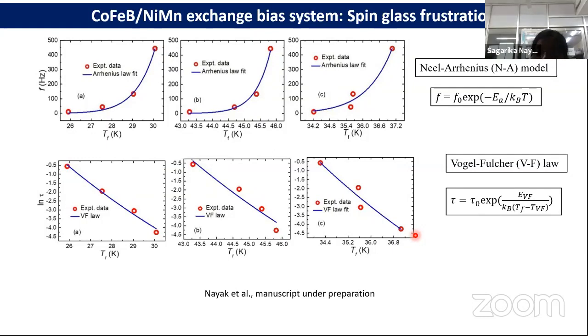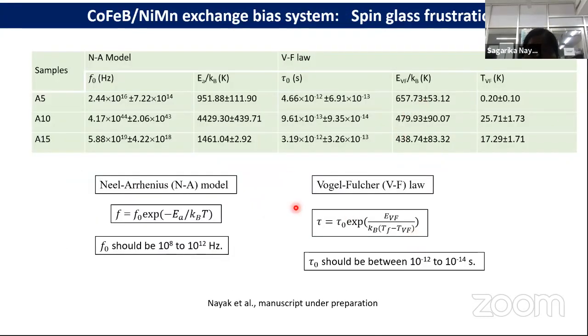Next slide, I'll describe with the data. We found that for a spin glass system, the tau 0 should be in the range of 10 to the power minus 12 to 10 to the power minus 14 seconds, which very well agrees with the system being spin glass like, frustrated.